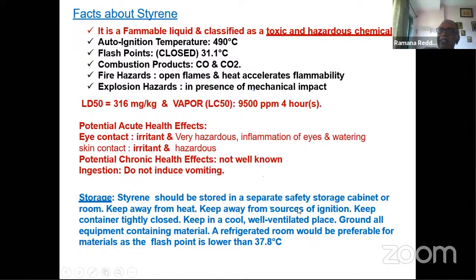So at 31 degrees temperature, if the control goes off, in Visakhapatnam, you can imagine, we reach 31 degrees just like that, in most places in Andhra Pradesh. So whether the temperature controls failed or they were switched off to save power, we don't know. Combustion products are CO and CO2. This is the point I want to emphasize later. Fire hazard: open flames and heat accelerate flammability. The heat, the surrounding ambient temperature, might have accelerated the flammability. Explosion hazard: in presence of mechanical impact, there is a chance for explosion. Unless there is a high temperature, there is no chance for explosion. So both things might have taken place.